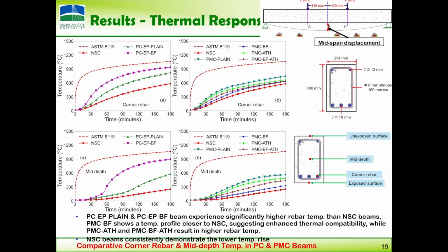This is the normal strength concrete beam. Here as well, normal strength. This is the polymer modified concrete beam. Notice here, at close to 2 hours, you will get that 600 or so. So it is delayed in the case of polymer modified concrete. So these are the temperatures in the rebar. This is at the mid depth.